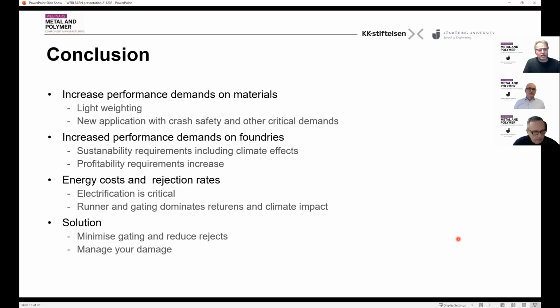Electrification is critical, and if you reduce your returns in the foundry, you will have a lesser amount of energy per product being used. And since the runner and gating dominate the climate impact, this is something that we need to work with. So the solution to all these issues is to minimize gating and reduce rejects by having control of your melt. And that means manage your damage.